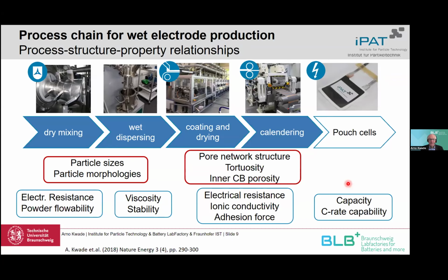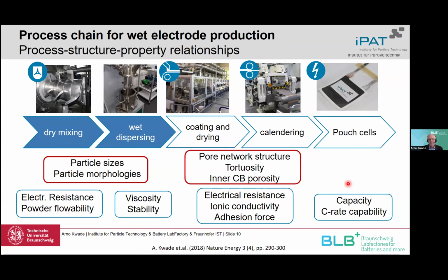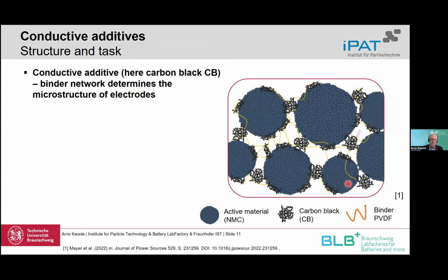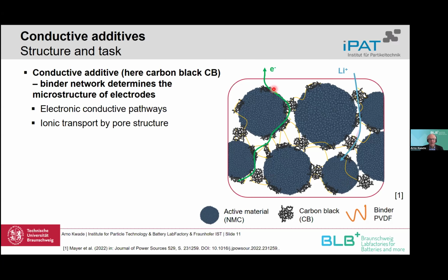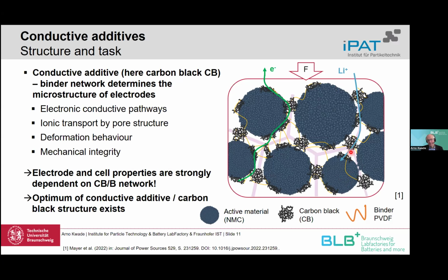of the cells. So now, first focusing on dry and wet mixing, we have the task to disperse the conductive additives, and I will focus here on carbon black, but today CNTs, carbon nanotubes, are almost always also inside the electrodes, and their dispersing is also very crucial. And this carbon black determines, besides the CNT, the microstructure of the electrodes. And we need, like it's shown here by the green line, a good electronic pathway. We need good ionic transport through the pores and also through the pores of the carbon black. And it also determines the deformation behavior and mechanical integrity, and by that also lifetime, but also production properties of the electrodes.